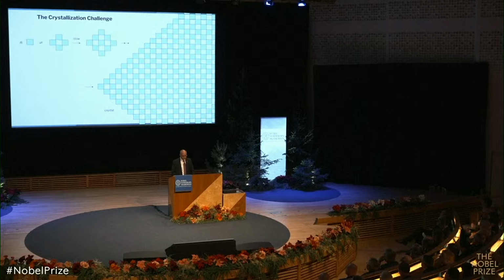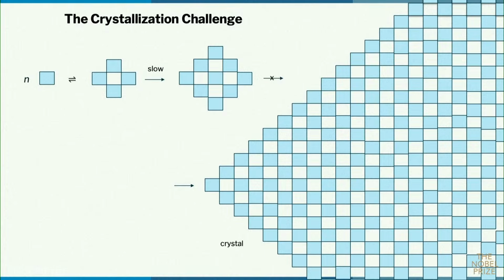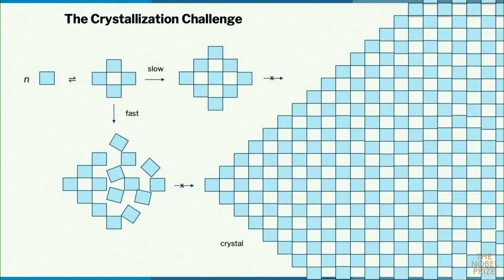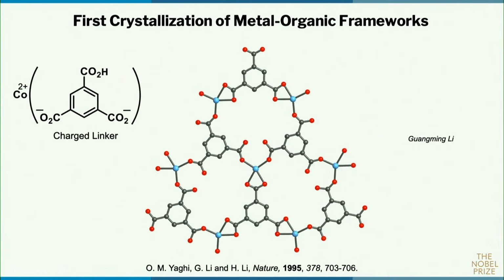The second important thing is that this process of coming together and separating needed to be at the right speed. If it's too slow, then you don't make large enough crystals. You make fragments. And if it's too fast, then you make that awful hump I was talking about, this amorphous, ill-defined material. So that was the challenge that Guanming solved. She found the recipe that would take, for the first time, a charged linker, such as carboxylate, with cobalt-2+ to crystallize the very first MOF. So that was a big success made by Guanming Li. Guanming Li, remember, is the young student that came to me and I pushed her away. Now she is successful, and 20 years later,